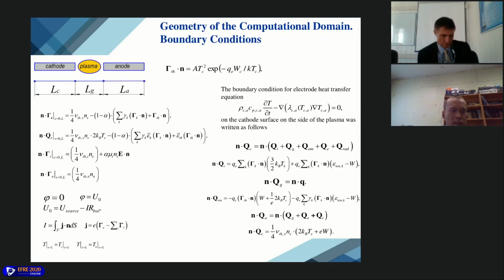Also, as a boundary condition of the Poisson equation, we assume that the cathode was grounded, and on the anode we input some voltage, which is found from this equation. We determined the boundary condition on the temperature of heavy particles at the cathode and the anode from the solution of the thermal balance equation of the electrodes on the cathode and the anode.